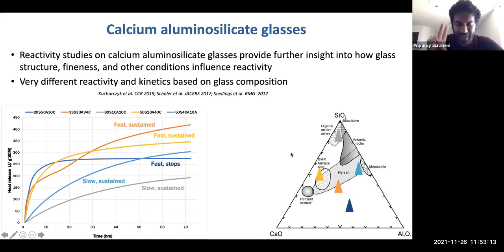And the 2 compositions which have all 3, calcium, alumina, and silica, these are the most interesting because there are high amounts of all 3. These are the most interesting because not only are they fast, but they're also sustained. And ideally, this is the sort of behavior that you want, where you want your reactivity to be increasing very fast, but not to stop. You want it to keep on going along. So we're investigating more into the glass structure, how that drives reactivity, the possibility of developing some of these very unusual glass phases, blending of certain materials, etc.